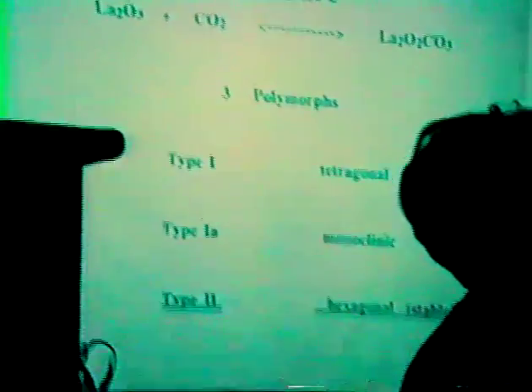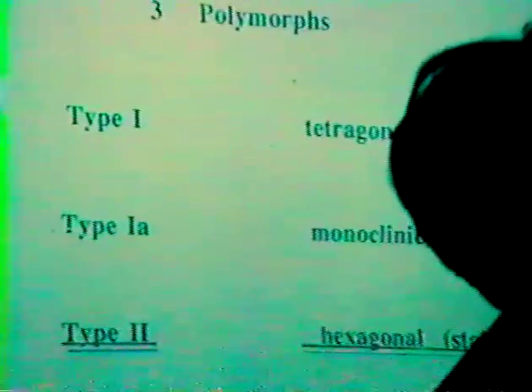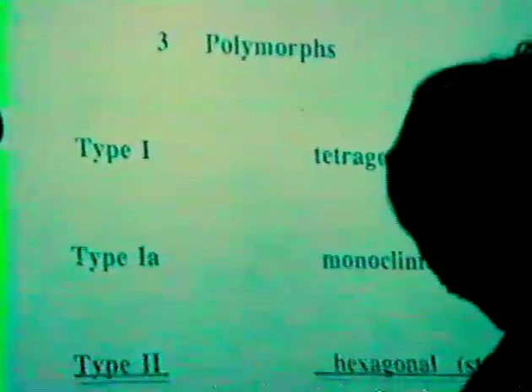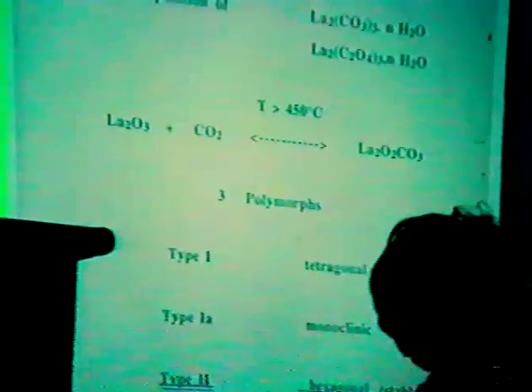Oxycarbonate can be obtained either from the decomposition of the oxalate or the carbonate, or, as I have told you, by direct carbonatation at a temperature higher than 450 degrees. There exist three polymorphs: type 1, which presents the tetragonal structure, type 1a corresponding to a monoclinic structure, and type 2, which has the same structure, the hexagonal structure, as the parent oxide. This is the stable polymorph.